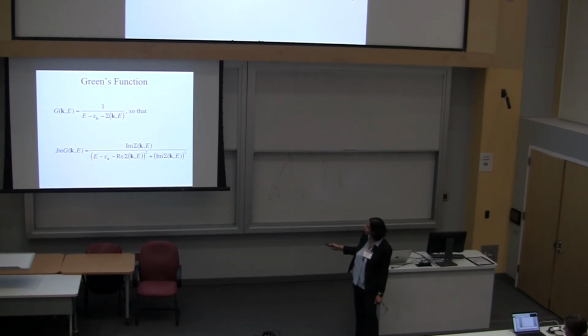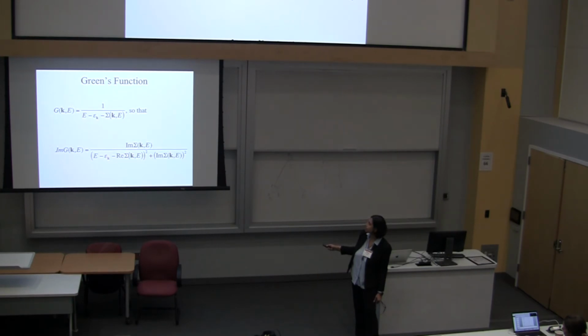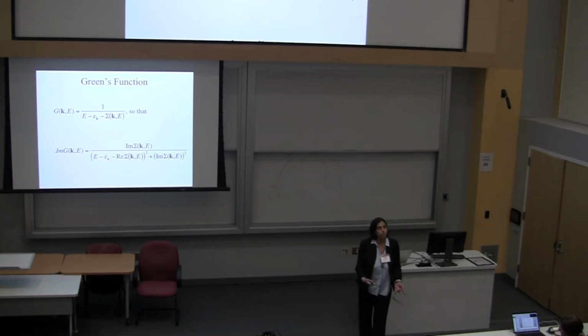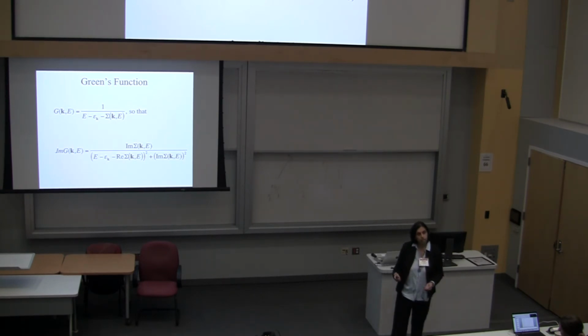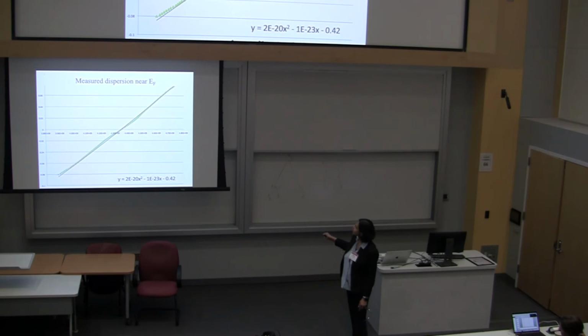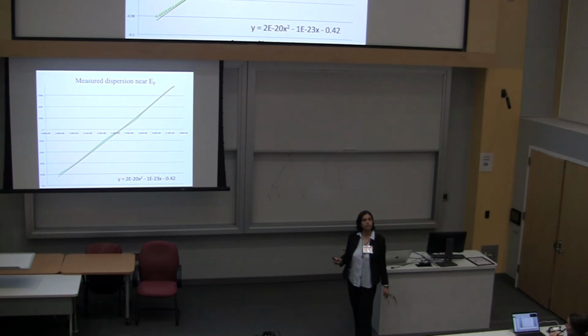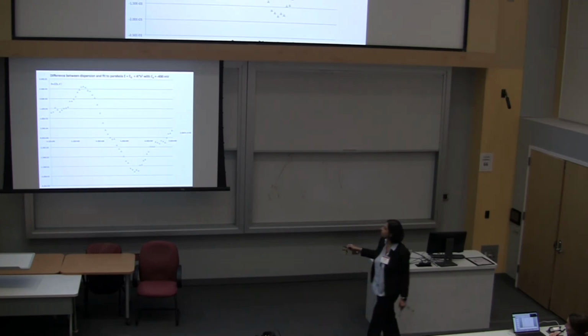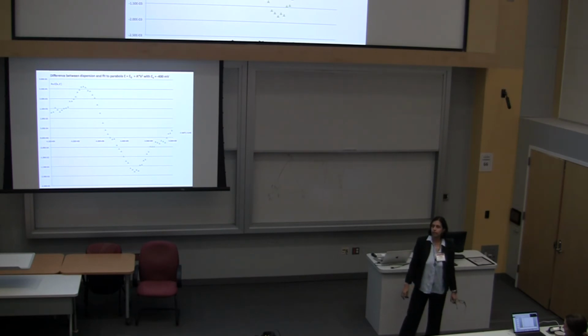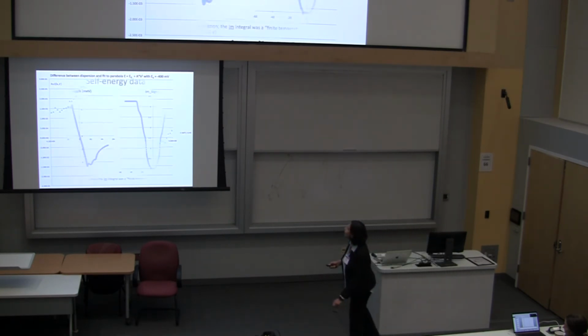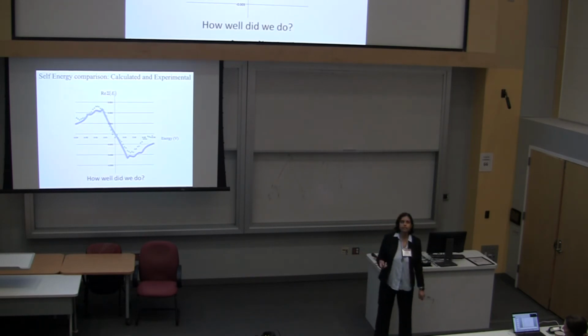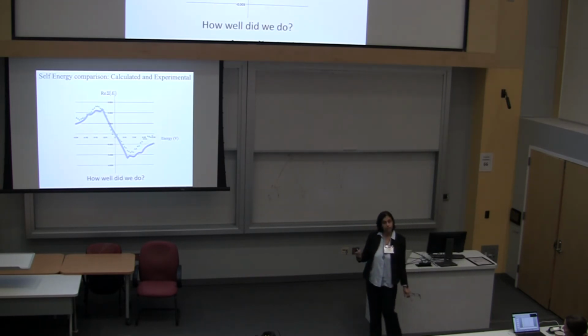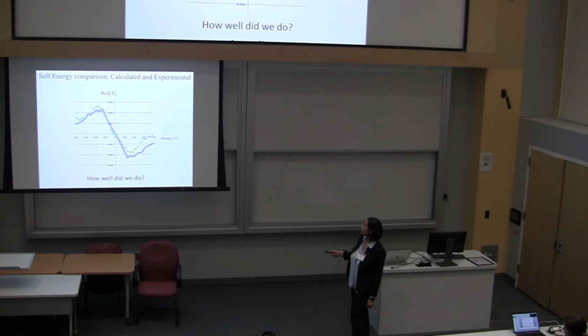So the real part of the self energy simply shifts the bare dispersion. So in order to get the real part of the self energy, if we knew the bare dispersion, we could subtract the actual measured data from it to get the self energy. This is the bare dispersion extrapolated from high energies. You subtract the two, and there you go. This is the real part of the self energy. Okay? And now we can compare the calculated self energy with the measured self energy.